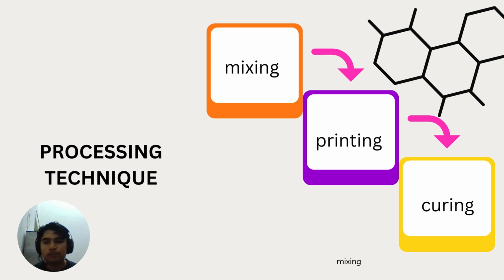And lastly is the curing process. The curing process is completed in the last phase to strengthen the bonding between the particles of filler, binder, and hardener. Curing was also used to melt and harden the mixture with the assistance of a hardener to increase the adhesion between the ink and the substrate. The curing procedure ensures the graphene is adhered to its substrate, which improves its mechanical and electrical characteristics.